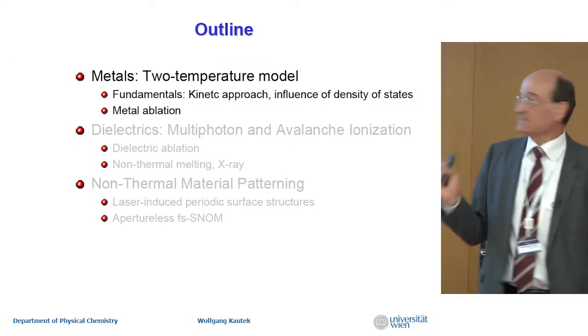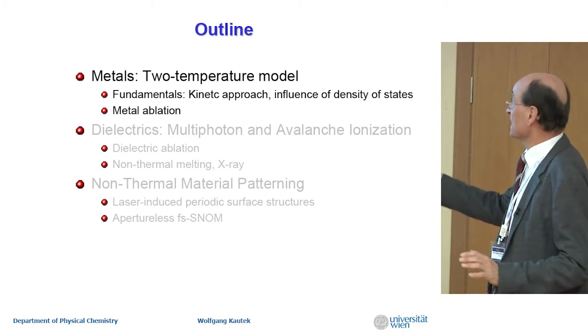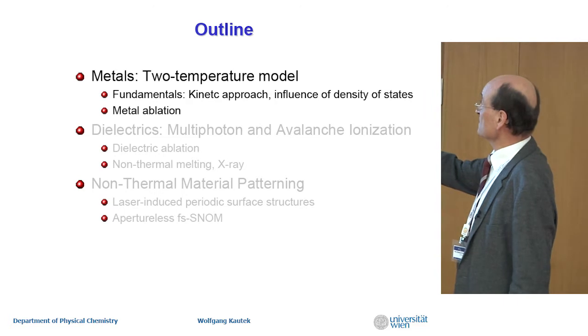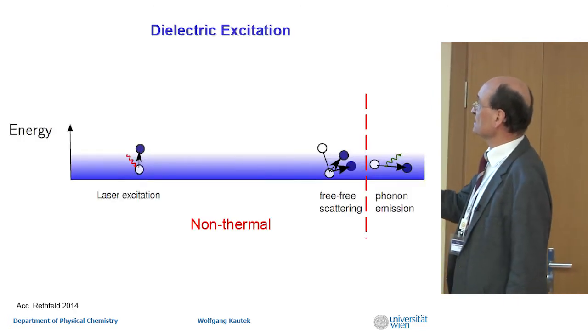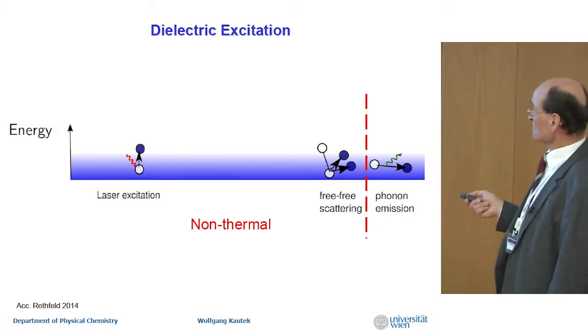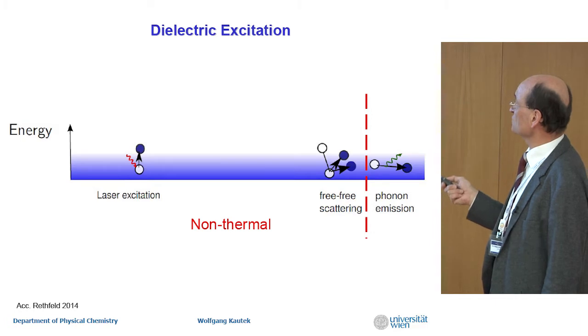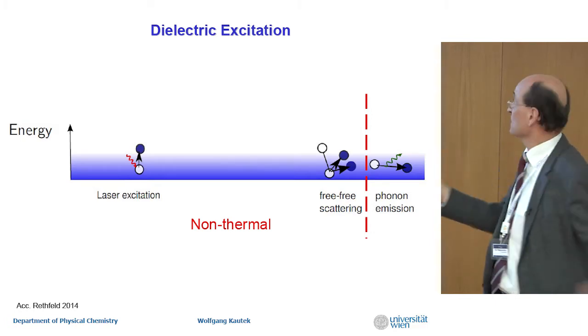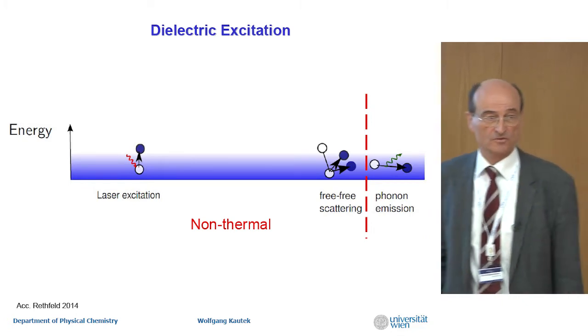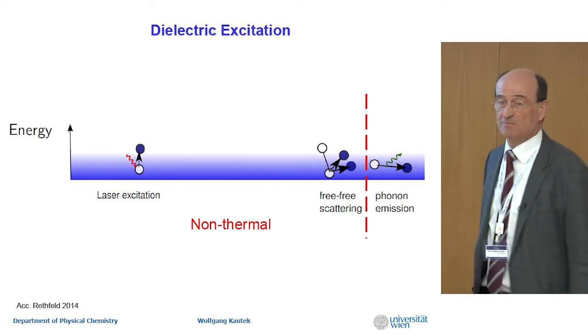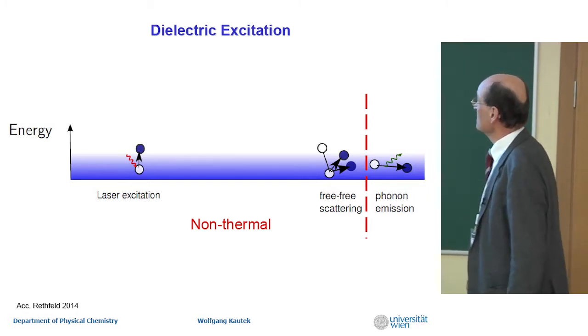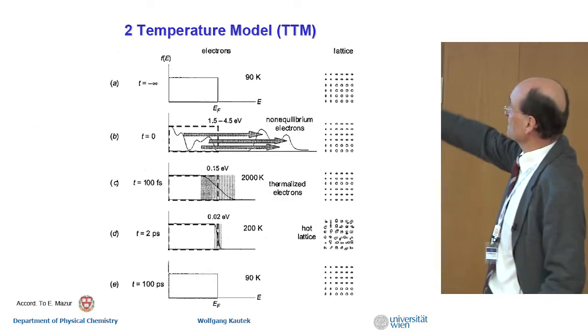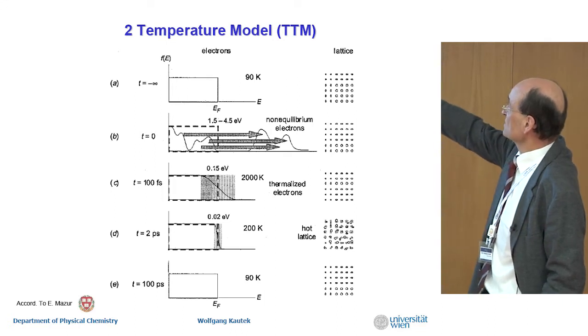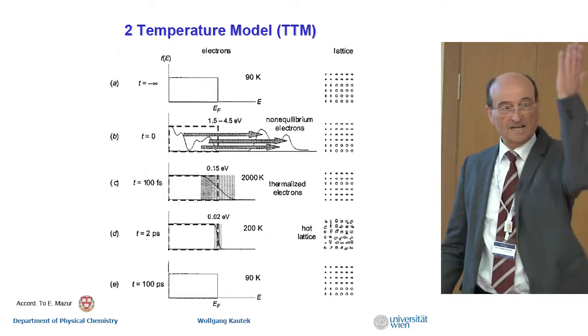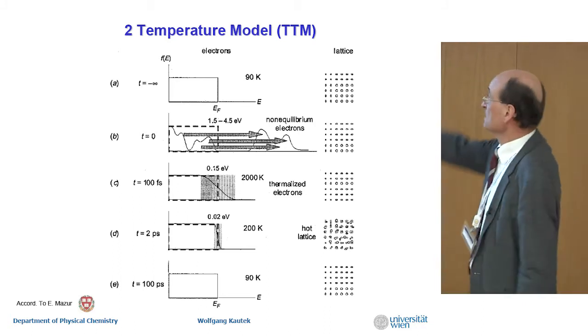Now, I want to give you a short glance into this world of metals, dielectrics, and then at the nanopatterning. First, the metals, very, very short. You have excitation in the metal above the Fermi level. And at the end, you have first a free electron scattering, Maxwellization, and then a phonon emission, and then the material is hot. That's quite simple, but there is a time delay between non-thermal and thermal. So that's another picture. Here's the electronic system, and here's the lattice symbolized. So your start here is the Fermi level, the energy, the population, and you are tearing out the electrons when you excite. The lattice doesn't know that at short time.